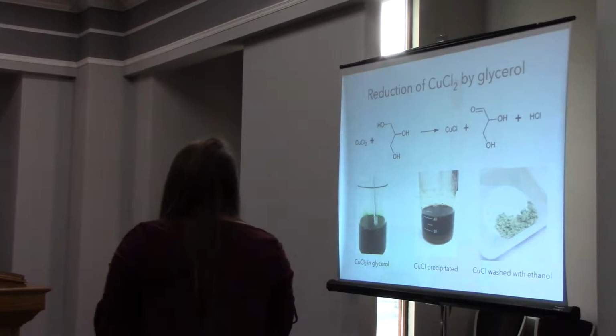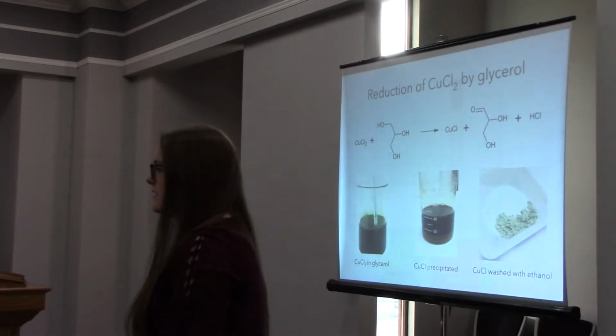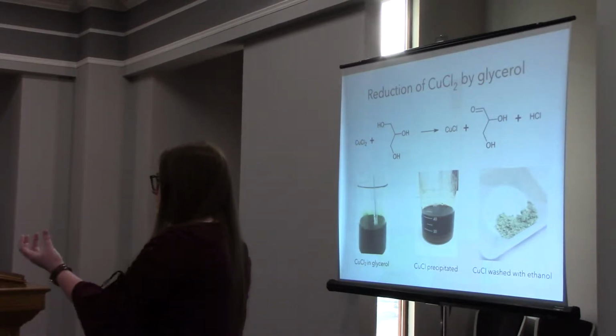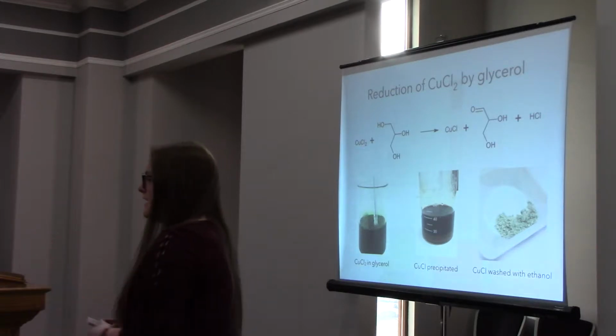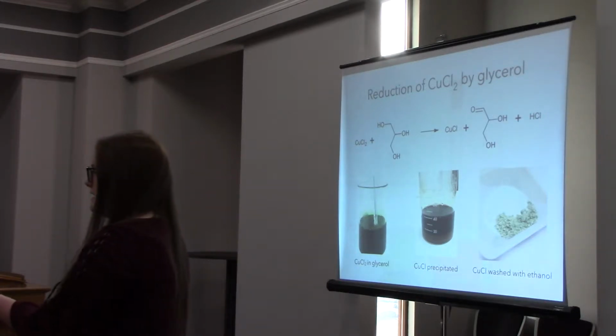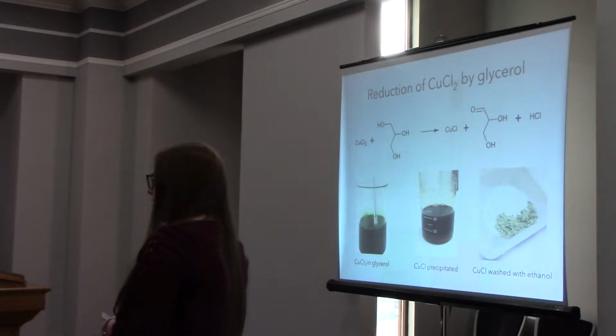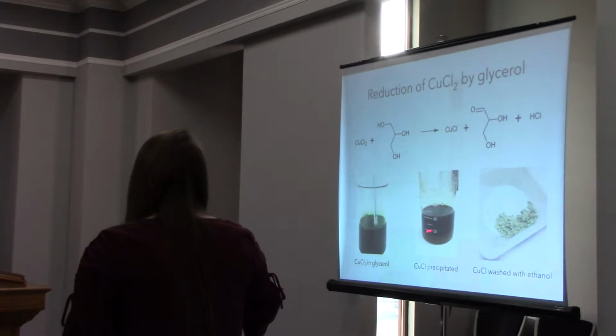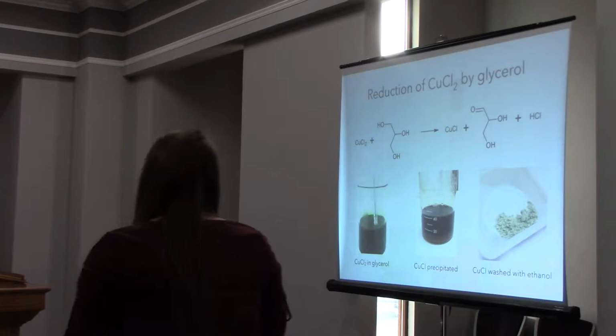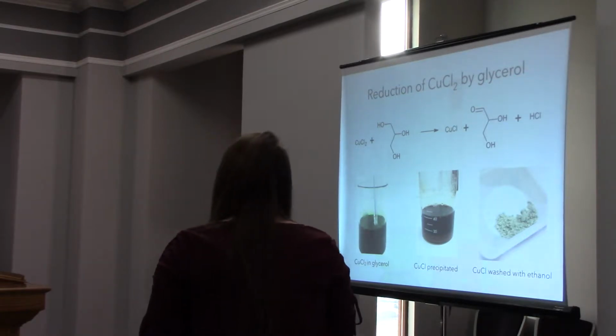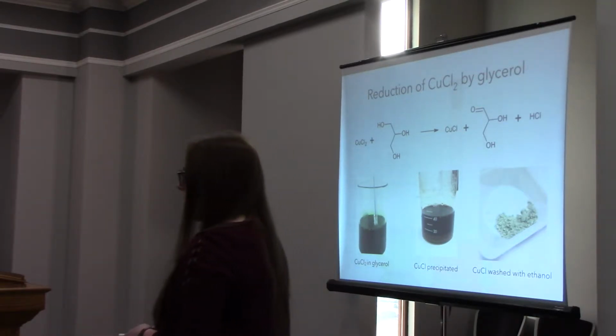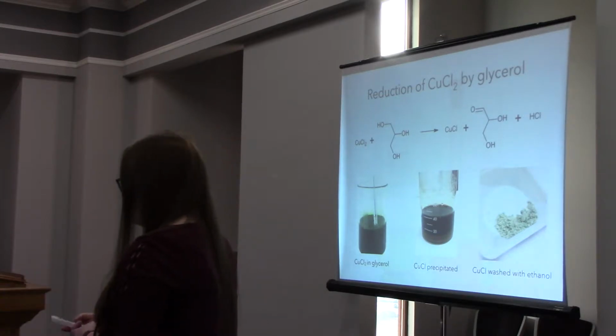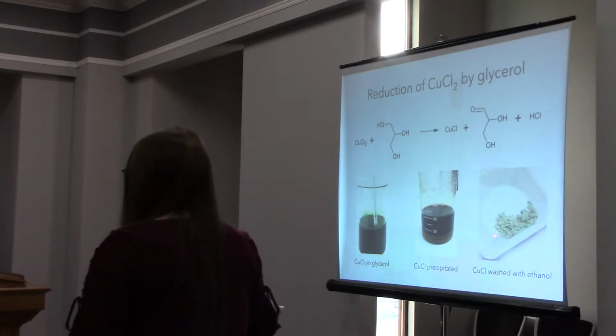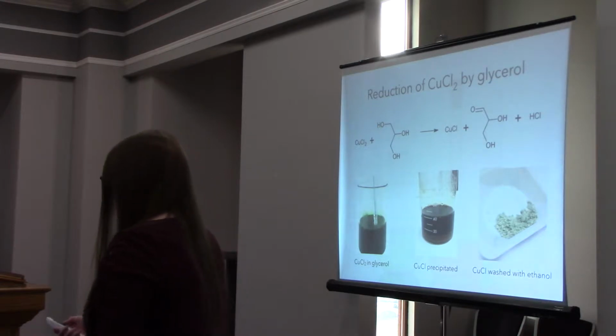Here's the reduction of copper 2 chloride by glycerol. The copper 2 chloride in glycerol is kind of like a green liquid, and we let it heat up to about 170 degrees and then cool off and sit there, and the copper 1 chloride precipitated out of it into this layer at the bottom with this dark liquid on top. And then we washed the copper 1 chloride with ethanol and dried it, and so it created this powdery substance with the copper 1 chloride.